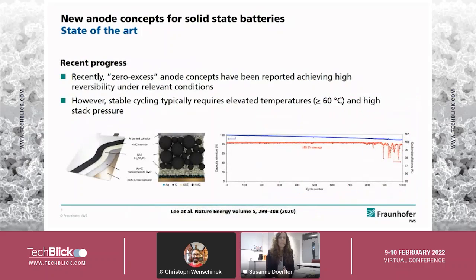So what are the solutions? I think the most promising and very prominent solution was given by Samsung SDI. They solved this problem by employing a carbon black matrix with some silver nanoparticle sprinkles. This layer and scaffold enables a better plating and stripping mechanism of the lithium. They showed a pouch cell with 900 watt hours per liter and 1000 cycles.